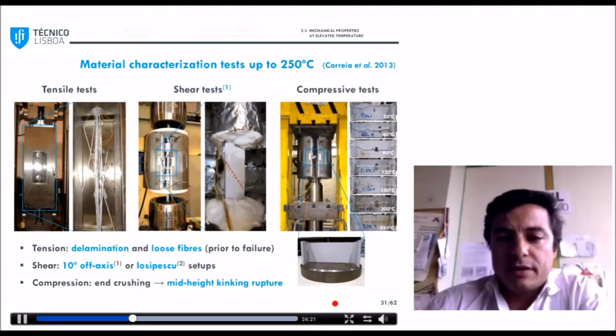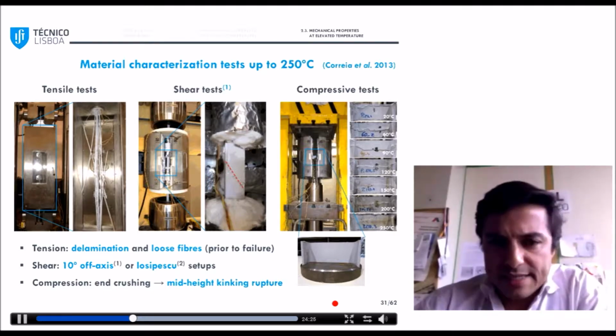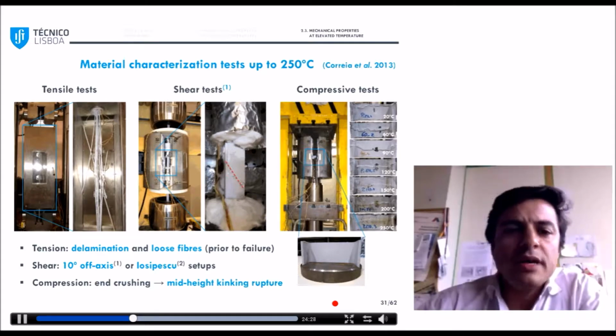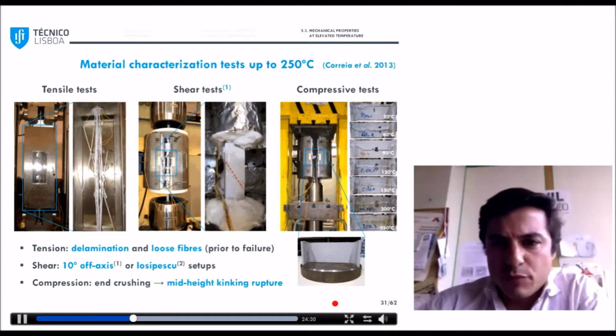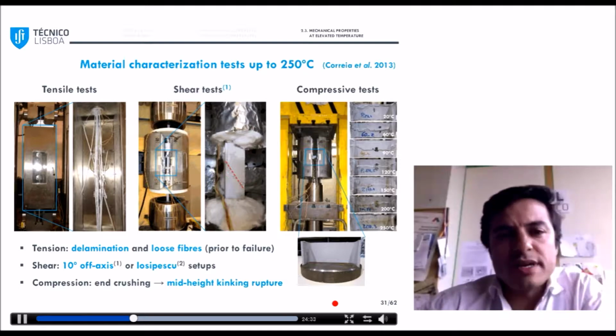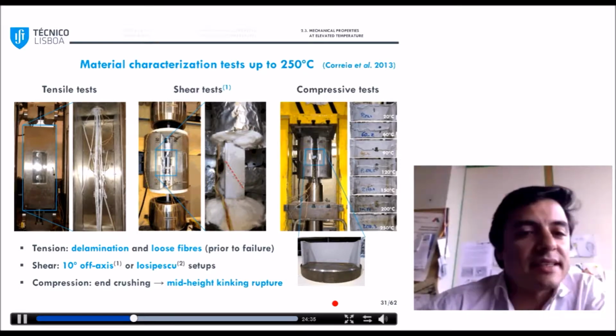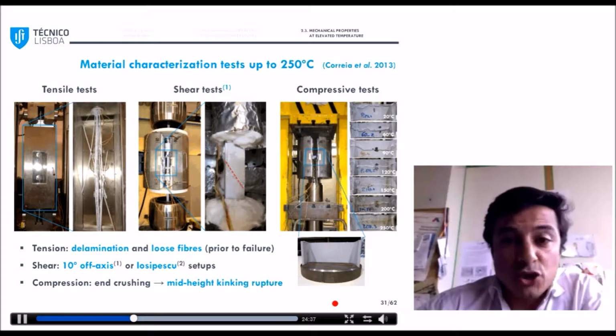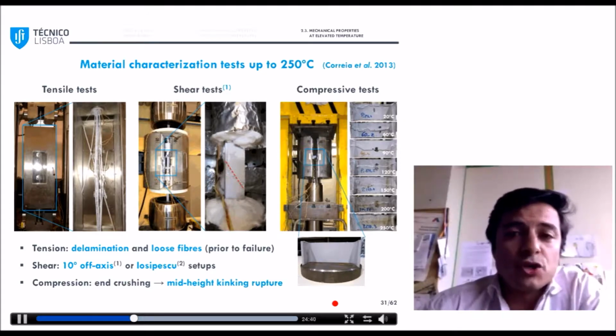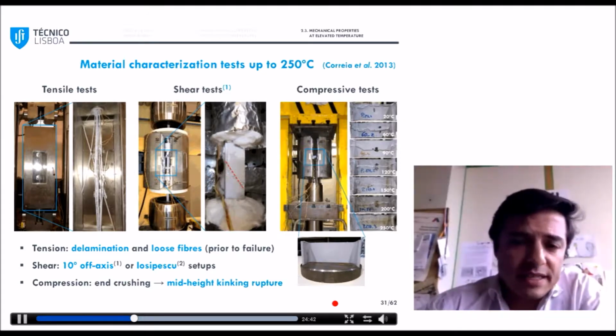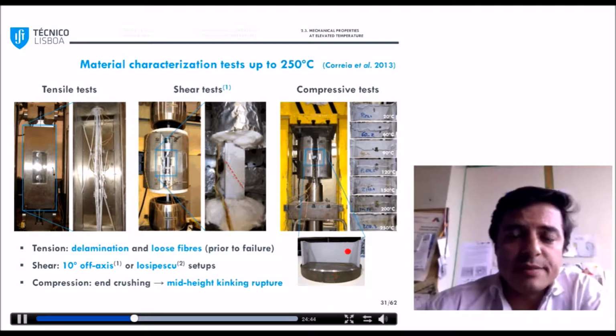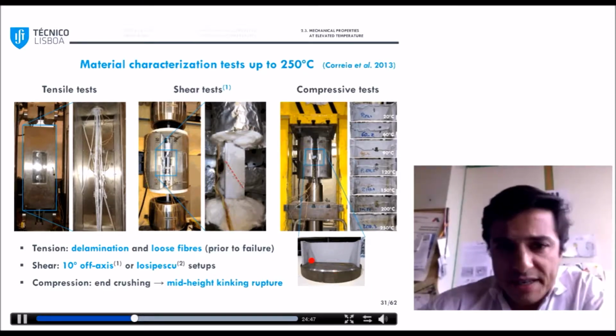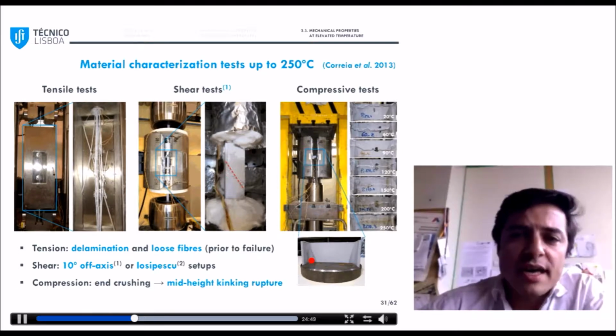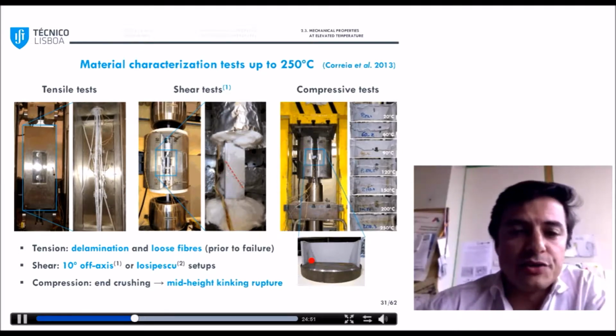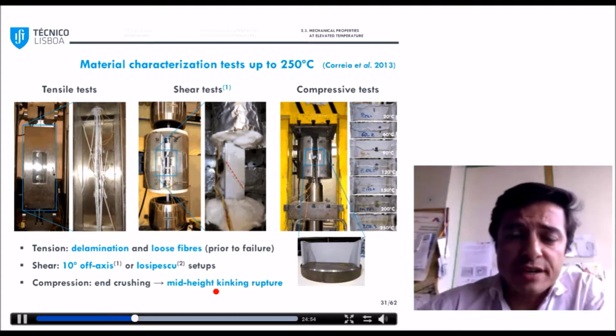So in this specific topic at IST, we performed a set of mechanical tests in pultruded GFRP material in tension, shear, and compression from ambient temperature up to 250 degrees. You can see the setups in these pictures. So the procedure was quite simple. We used laminates or I-section segments for compression. We first heated the material to the target temperature and then loaded the material to failure.